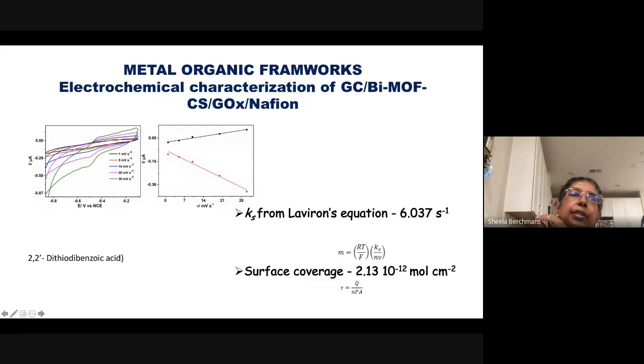Also, we have used different types of compounds, metal organic frameworks, for the immobilization of enzymes. We prepared a bismuth-based metal organic compound using the ligand 2,2'-dithiodibenzoic acid, and we have incorporated glucose oxidase enzyme onto this metal organic framework, and we have observed the direct electron transfer of the enzyme. That is, we can directly wire the enzyme to the electrode surface. So we can see the FAD electrochemical signature. FAD is the prosthetic group of the glucose oxidase enzyme.